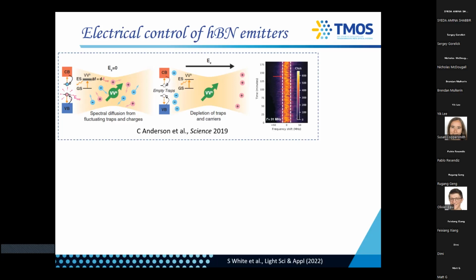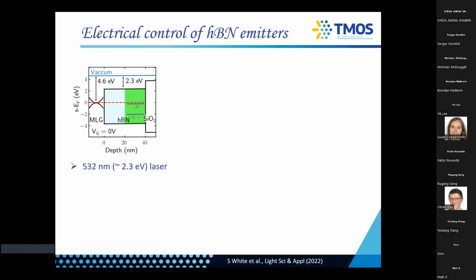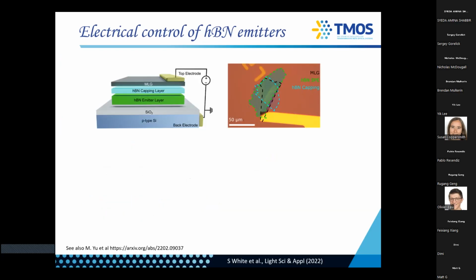Yeah, exactly. We haven't done it. No, we haven't thought about it either. We tried only once. I think it was nickel oxide, hBN, graphene, and we didn't really see much. But the reality is that we don't really know if our graphene is P or N type. We don't really know how to do these measurements properly. So what we rely on is we just make the device and we measure IV curves from this type of device and we see the IV curve behavior basically. But we don't check the graphene beforehand to know if it's p-type or n-type.